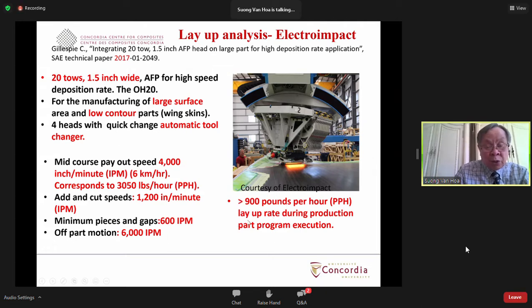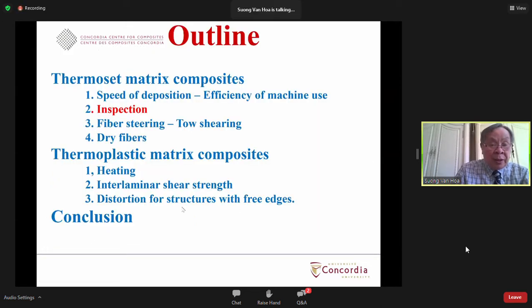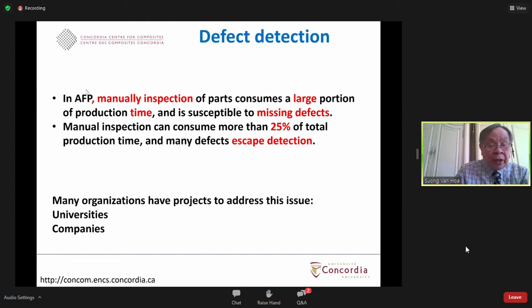So that shows the speed of material deposition. The next aspect here is inspection. That means how much time you have to spend to inspect. In the past, a lot of AFP parts were done by manual inspection, and that consumes a large amount of time, and sometimes you may miss the defects. The time can be more than 25% of the total time, and defects may escape detection.